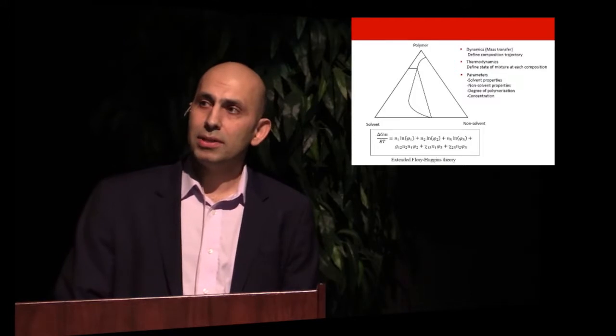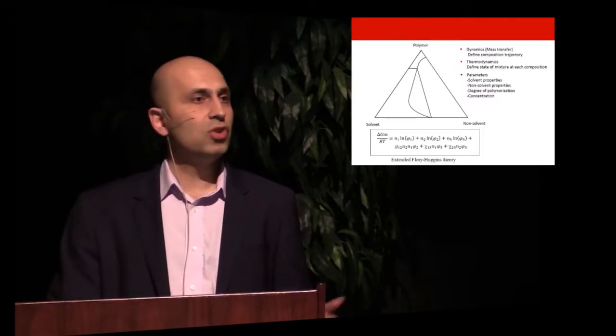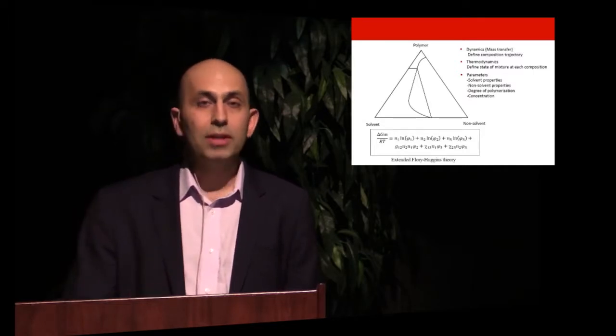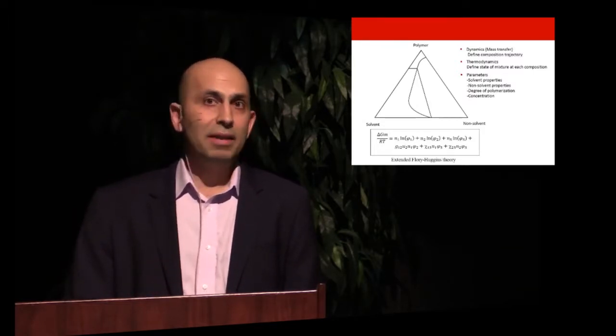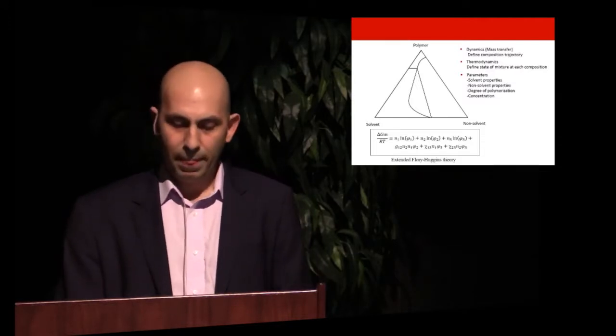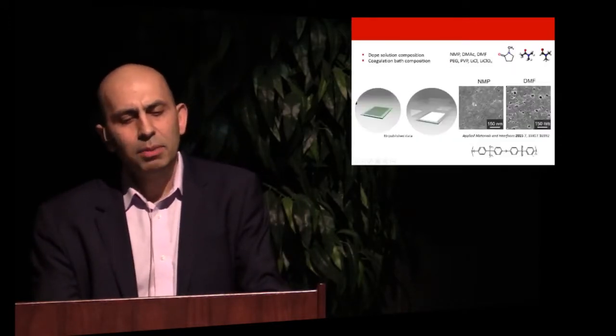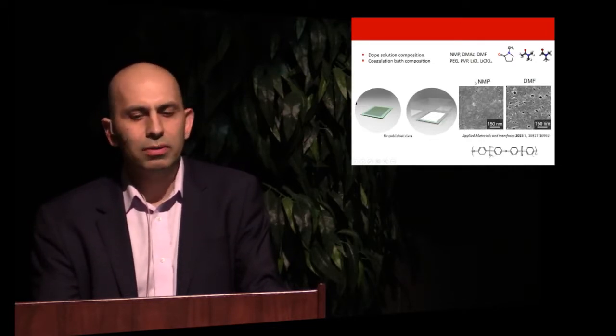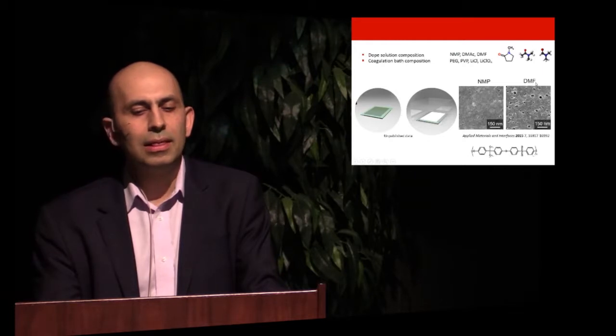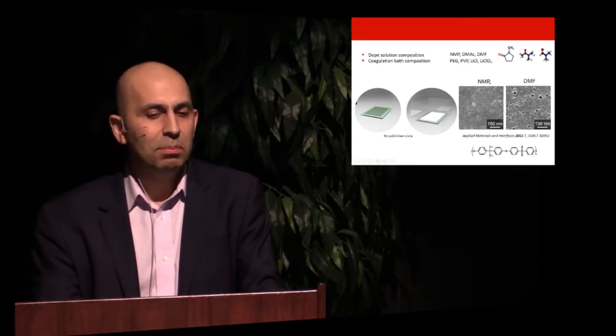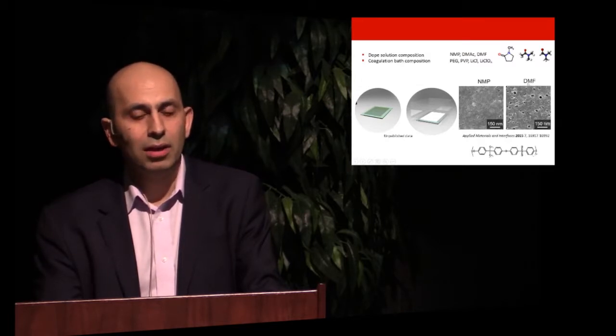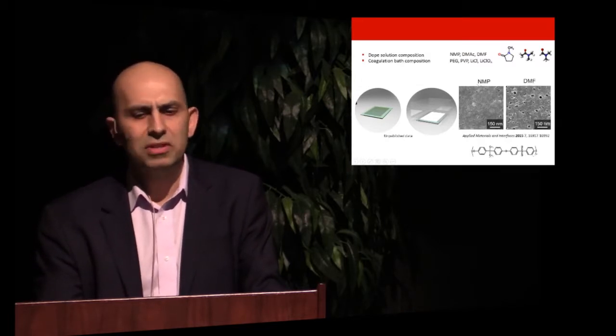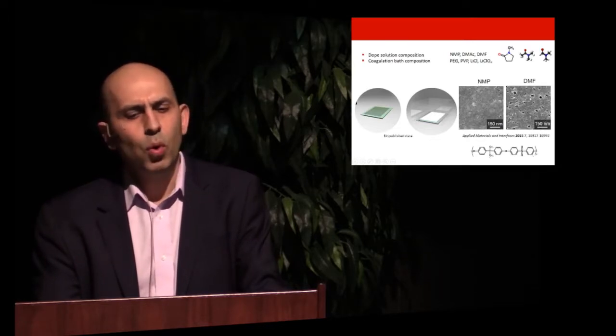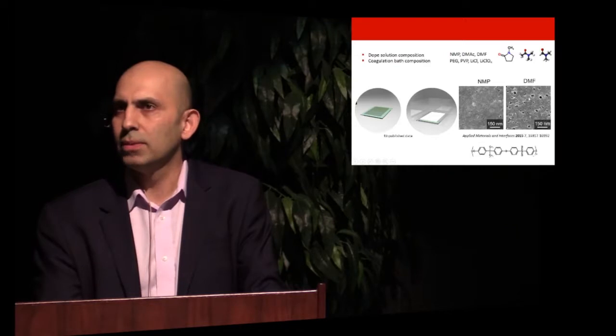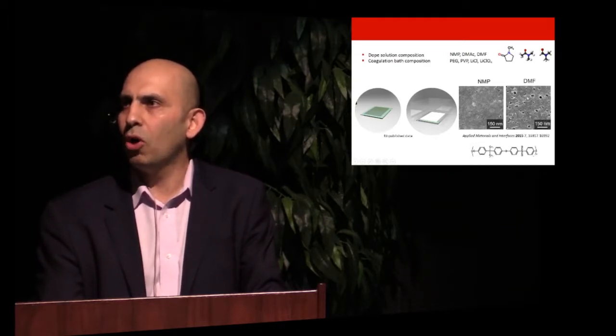So we can simulate this. We can try to understand the effect of different parameters in the system, such as the polymer material itself, the solvent and co-solvent, the molecular weight, thermodynamics, and diffusion, and eventually design materials based on our needs. Here's an example. Here's a typical ultrafiltration membrane, like polysulfone. Here we just change the solvent. We have NMP, which is N-methylpyrrolidone, and we have dimethylformamide, so two different solvents. Everything is the same, and you see the pore size and the structure change significantly. So we can tune this property by simply changing the bulk property of the solution.